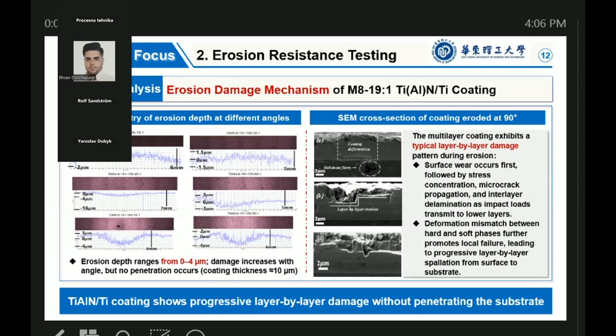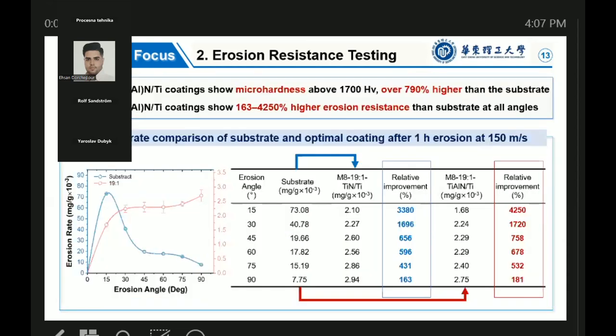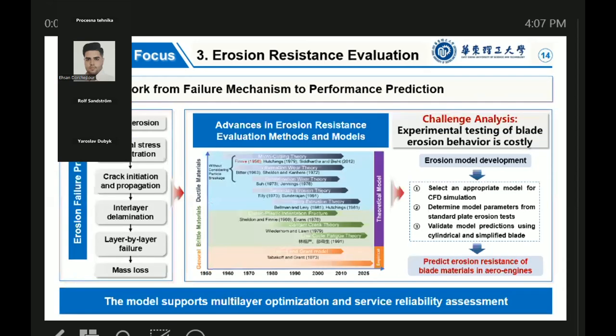The failure process follows a layer-by-layer delamination mechanism, starting with surface wear, then stress transfer, microcracks, and local delamination, eventually causing spalling from the surface inward. Compared with the substrate, the optimized coating achieved over 790% higher hardness and up to 4,250% better erosion resistance across impact angles.